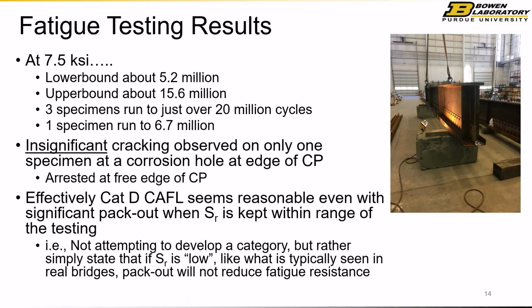Now, rivets are typically classified for first cracking as Category D, so we ran just over the threshold for Category D. Now, while that's good, it's also painful because you start looking at the cycle counts that you need. They get very high very quickly at low stress ranges when you're running just above threshold. Now, if you're familiar with the AASHTO fatigue curves, there's also what's called the design curve, the curve when you open up AASHTO you see. That's the lower bound curve, and that's associated with a 97.5% roughly probability of survival. In other words, if I ran a fatigue test to the AASHTO curve, it shouldn't crack.